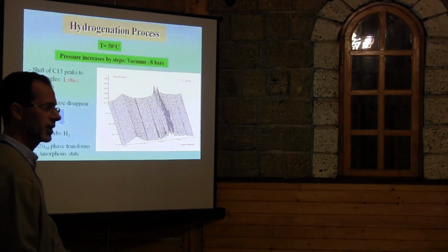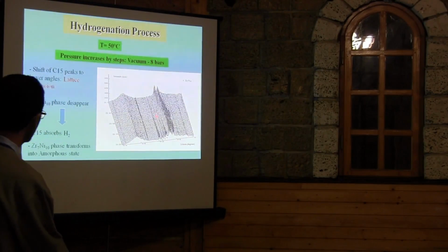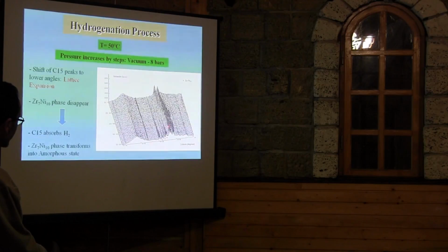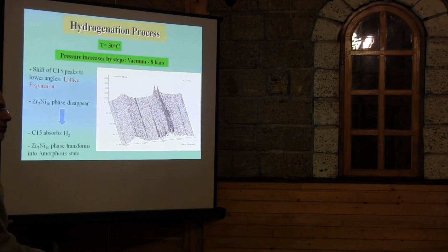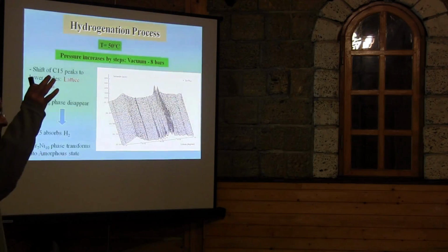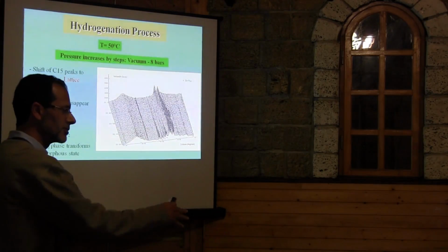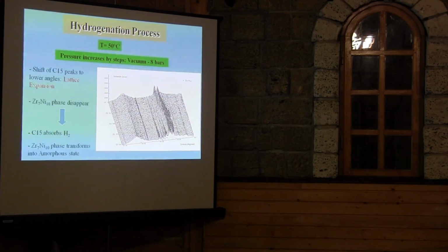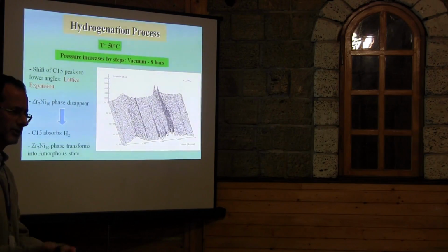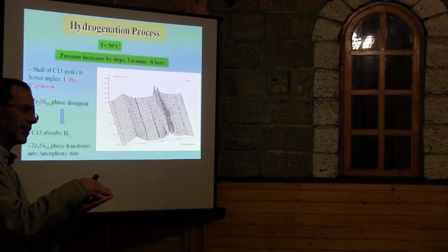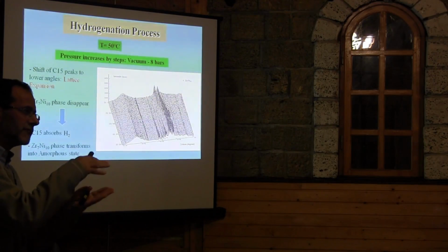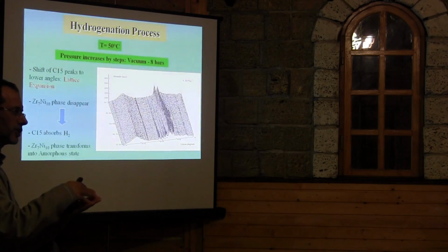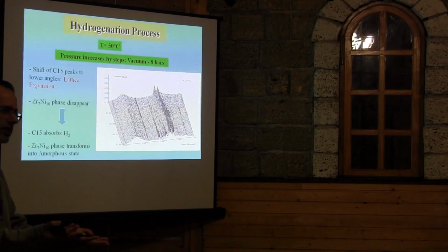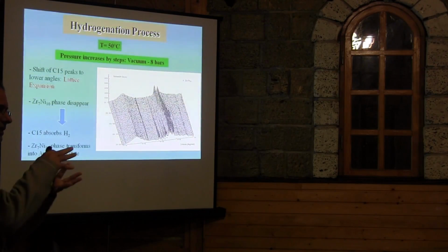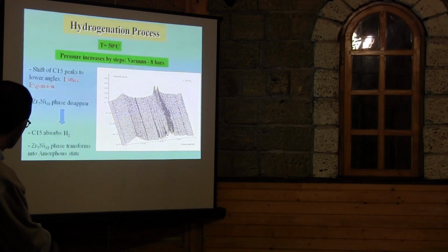As I said before, the interaction of hydrogen can change the crystalline phase. So it becomes amorphous. And then the peaks of this phase shift to lower angle. What does it mean in terms of diffraction? That means there is expansion of the lattice. Why? Because hydrogen goes inside. When hydrogen goes inside, you have lattice expansion. This is very important for me, because if I want to design a battery, imagine I make a battery like this, then after hydrogen absorption, the volume increases. When you make applications, you need to know the volume expansion. When you design a tank for hydrogen storage or a battery, you need to know this volume expansion. So imagine, I will show you the expansion of volume.